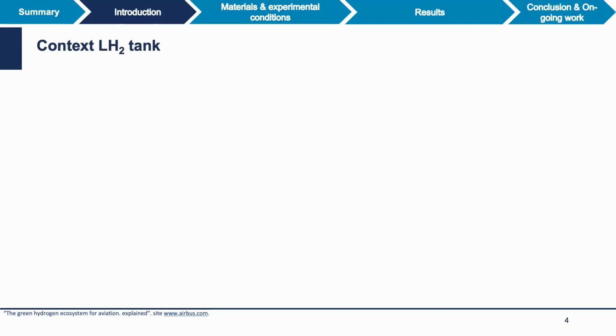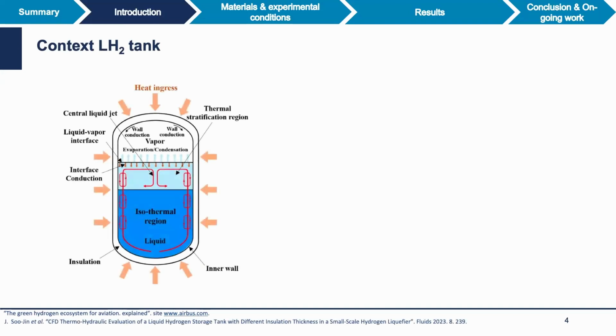Just a few words about the liquid hydrogen tank. So the principle is that you have two shells with a vacuum between the two shells in order to limit the evaporation of liquid hydrogen. So the temperature of liquid hydrogen is 20 K. So that means that the temperature of the material constitutive of the wall here is about 20 K also. But depending on the filling of the tank, you can have a temperature gradient in the upper part of the tank. So it will depend, as I said, on the filling of the tank. It can be a few or maybe 20 K, additional K.